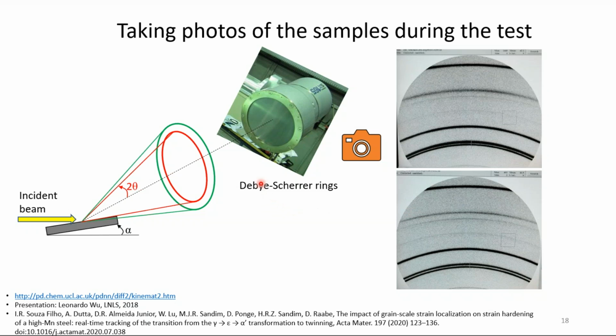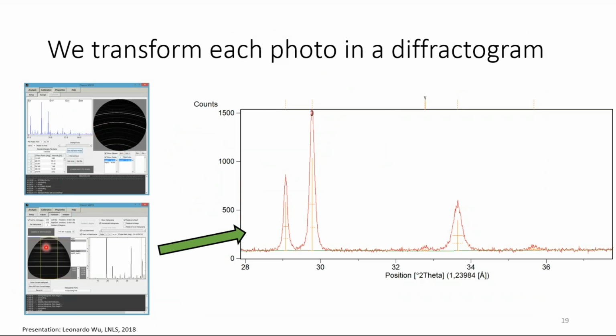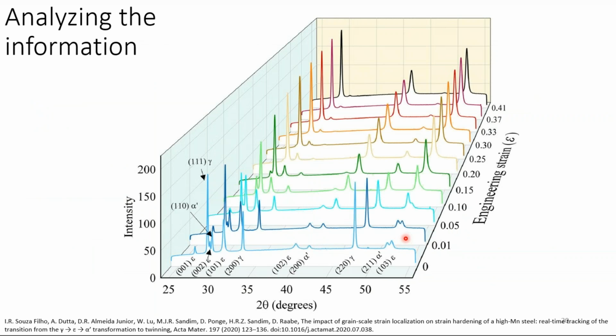During the experiment, you are going to have this detector here, and you have the incident beam coming to your sample, and then you are going to cause diffraction, and they're going to produce these diffraction rings, and then you are getting photos in this detector. For the size of the detector, in this beamline station, we are getting part of the diffraction rings. During the test, you can see the evolution of these rings. Some are going to appear, others disappear. However, it is difficult to quantify things here. You need to transform these rings into diffractograms. So you do that for all the photos you get during your test, and then you are going to get the diffractograms. After that, you are going to organize these diffractograms according to the order of your test.